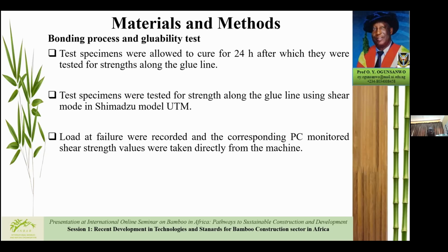The bonding procedure: in the bonding procedure, test specimens were allowed to cure for 24 hours, after which they were tested for strength along the glue line using the Shimadzu model UTM. The load at failure was recorded, and the corresponding computer readings were taken directly from the machine.